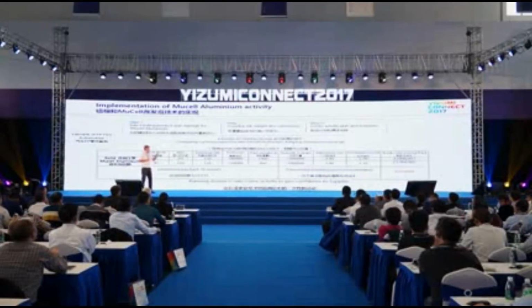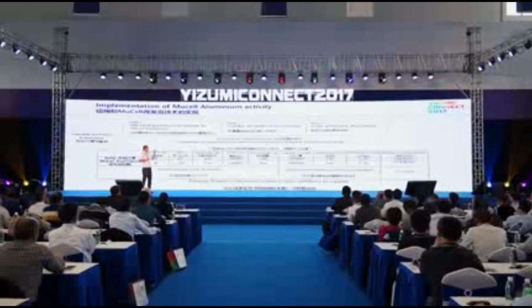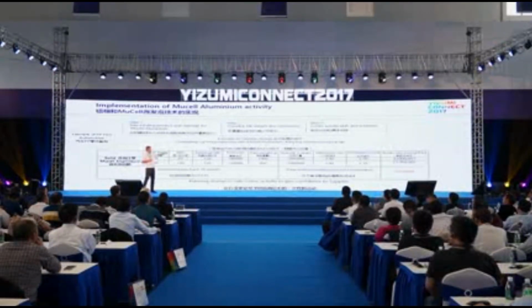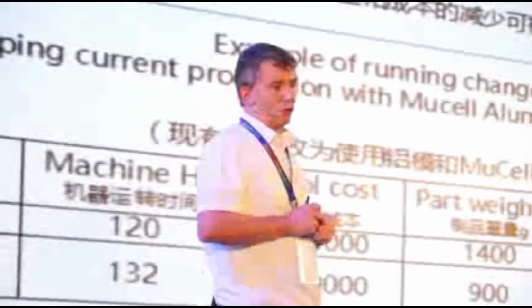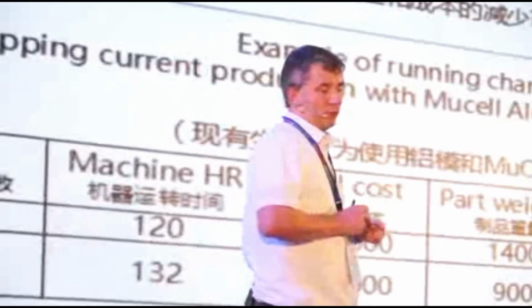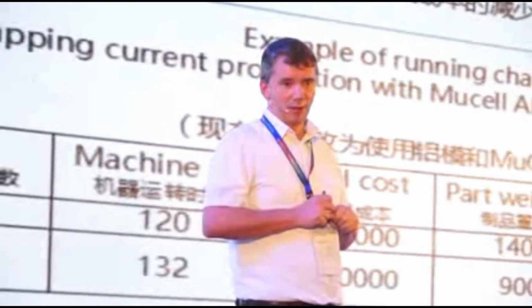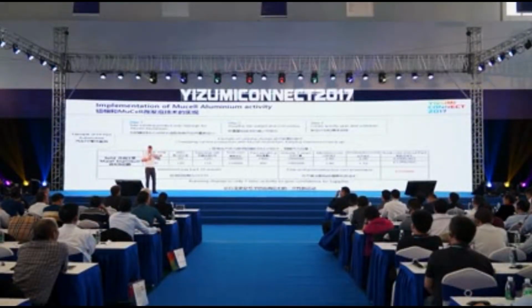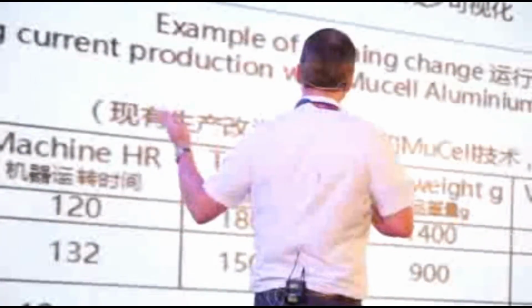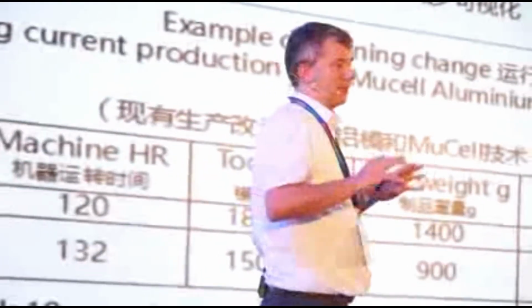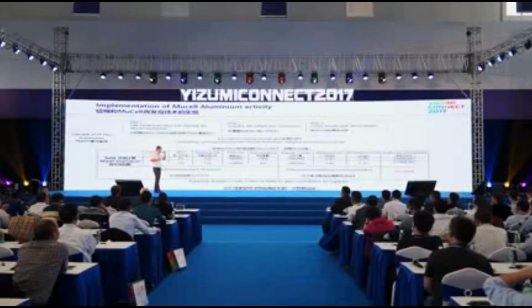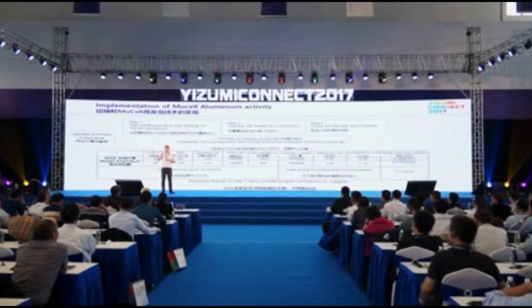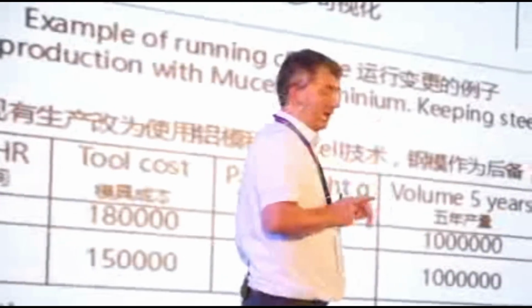And you can see that the material cost for the solid normal part was 2.8 euros. The cost for the MuCell Aluminium was 1.8. And the reason is, if you look at the part weight, 1,400 grams in solid and 900 grams after we redesigned the product and we changed to MuCell. So the production cost was much lower because the cycle time is much faster. So even with a small increase in the hourly rate, it's not really an impact at all. So the total cost for the life of this one product, plastic part, it was saved 1 million euros from its lifetime.